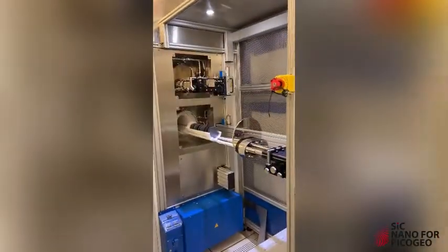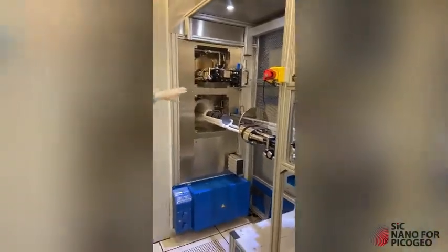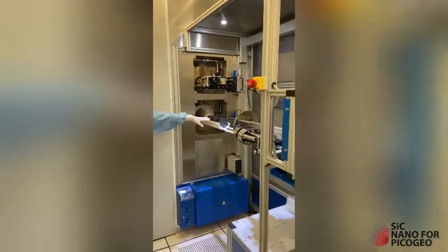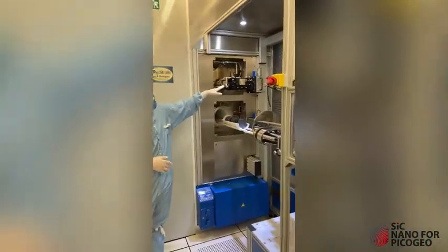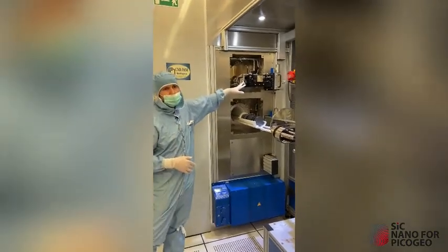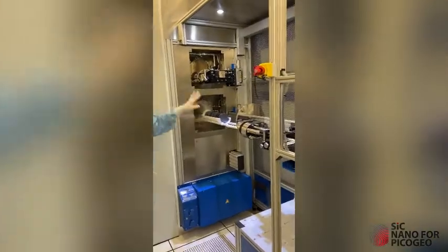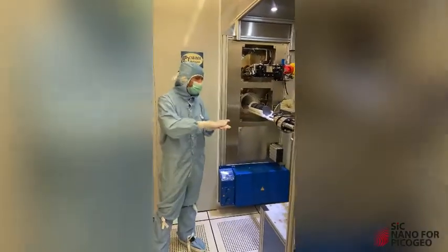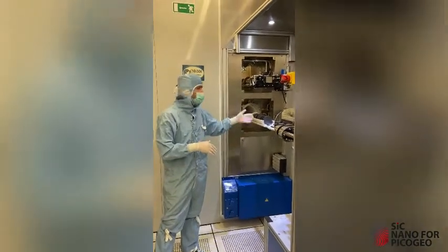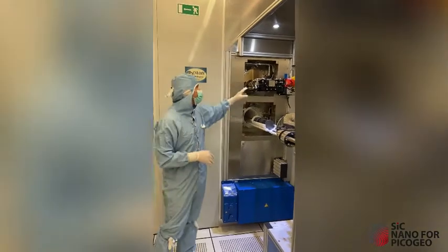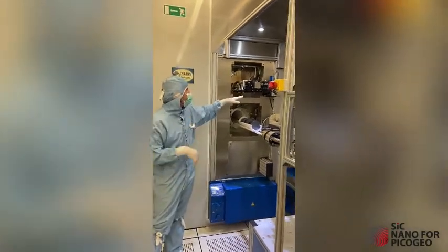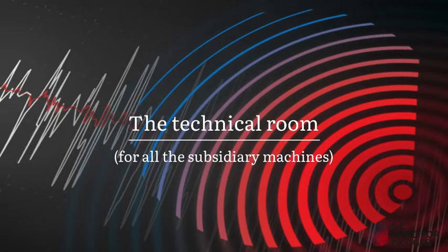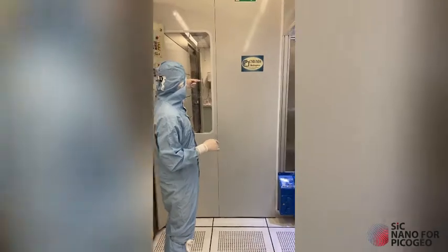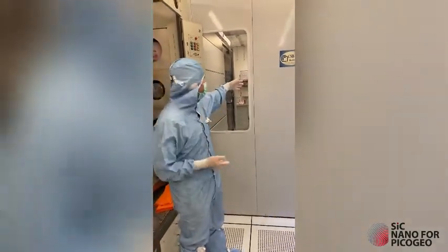Here we have LTO, low temperature oxide deposition, LPCVD deposition. Oops, no problem. No, it's a problem. These are two types: low temperature oxide with a gas source, and this with a liquid source. This is a very conformal oxide deposition, and this is a less conformal one. But this is used for higher thickness, let's say 1, 2, up to 5 microns. This is for thinner processes, let's say 100 nanometers.